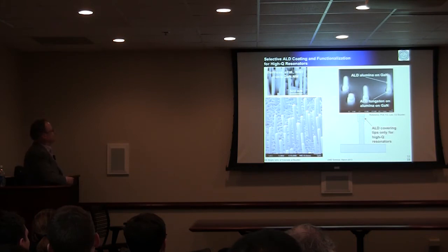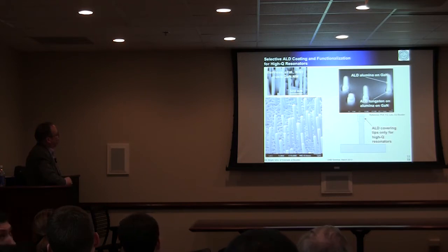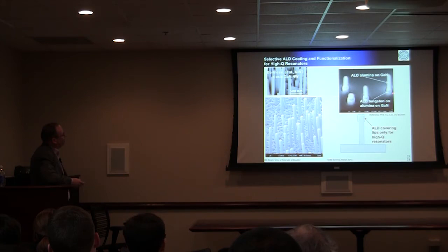So one more slide before closing this. The other work that we are looking at is, can you do concentric sort of electrodes on the nanowires? And this is a lot more challenging than one would think, but you can. And so what it shows here is a nanowire coated with alumina first, and then tungsten. And you put a layer of photoresist, and you can thin it down, and you can selectively remove the coating.